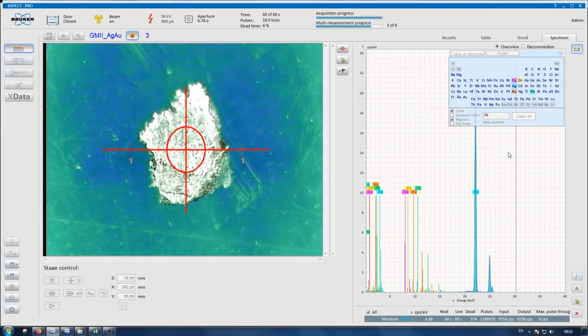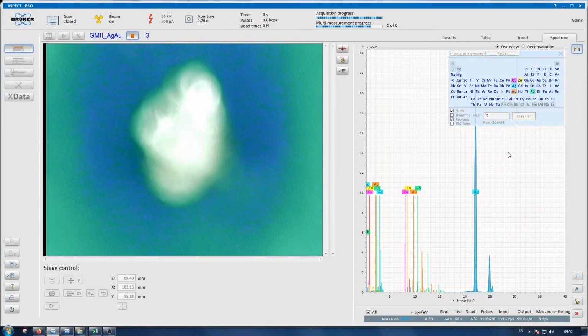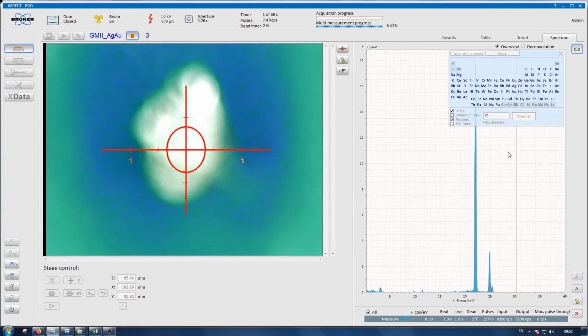The software of this machine memorizes the results of all the samples taken from the rhyton fragments. As you can see on the screen, all 3 samples taken from different points of the 2 fragments of the rhyton show particularly identical composition. Only tenths or hundredths of percentages of elements differ. The main composition of all 3 samples is a silver alloy, with more than 98% silver. Gold comes next, but its share in the total composition does not exceed 1.5%. Then there is a small amount of copper, with values ranging from 14 to 19 hundredths of a percent. Lead has the smallest proportion in the samples, with only 5 to 6 hundredths of a percent. No trace of zinc was found in all 3 samples.